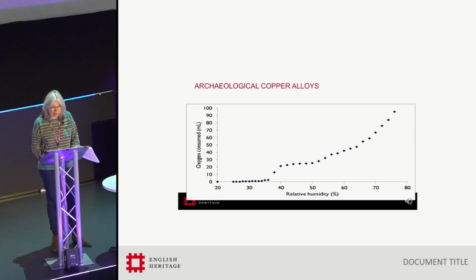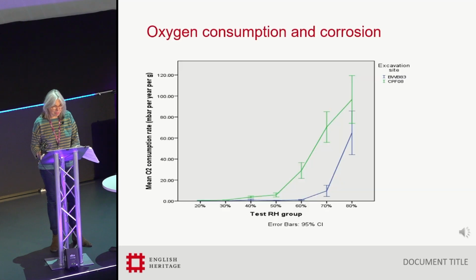The objects from the other site started corroding at about 60%, but really got into their stride at 70%. So the rate of salt-driven corrosion of iron is strongly correlated to the RH. However, the values can vary with material from different contexts.